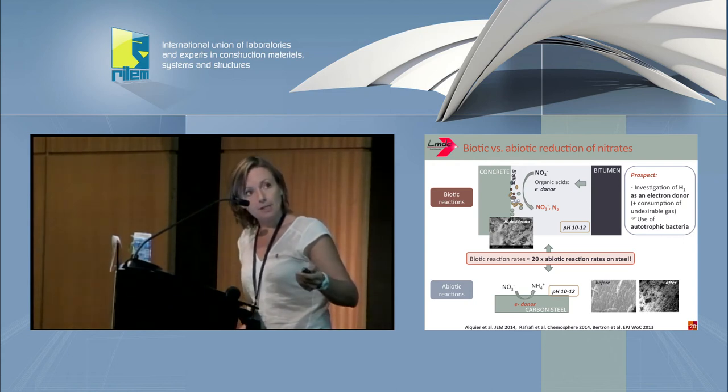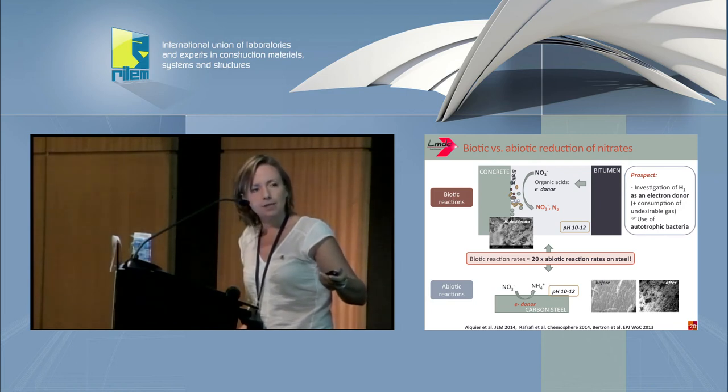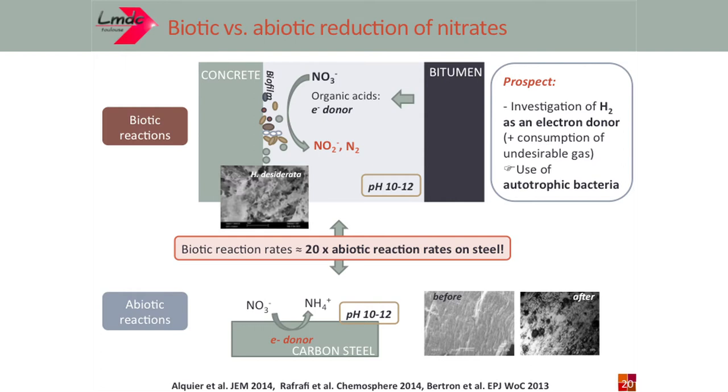At the beginning of the experiment, we didn't see any degradation. The steel was sound, and after we see very significant signs of corrosion. But what is most interesting is that when we compare the two experiments in the same chemical conditions, the biotic reaction rates are 20 times higher than the reactions that occur at the surface of the steel.